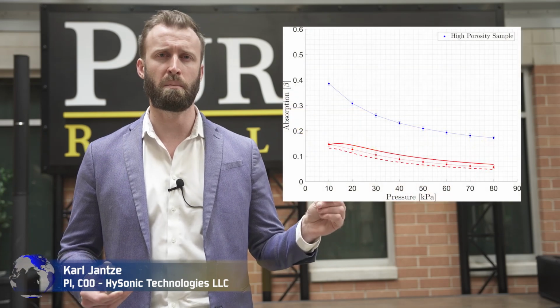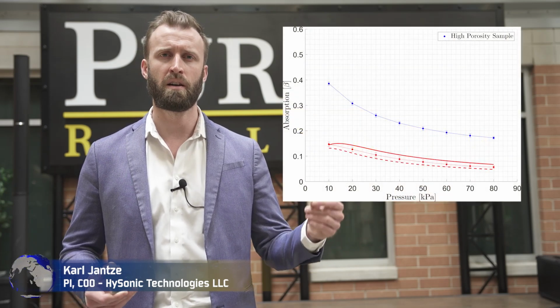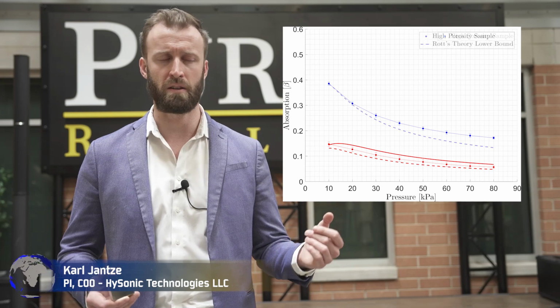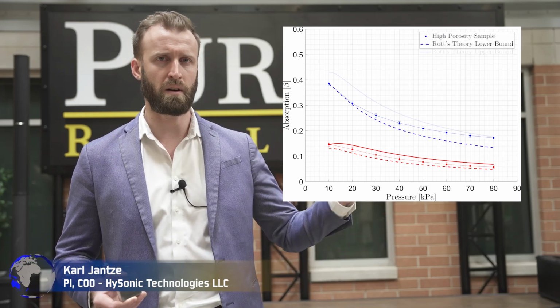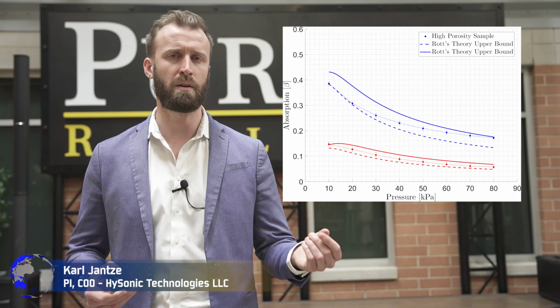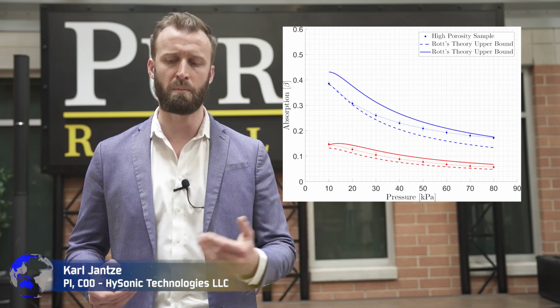In my hand here we have the high porosity sample, and similar to the low porosity sample, it contains pores that have a certain diameter and depth. The only difference is that it has more pores, allowing there to be a greater surface porosity. Very similarly, if we take a look, the experimental data is given by a blue dot that has an error bar, also representing the repeatability of these results. The lower curve and the upper curve also represent a certain tolerance above and below the nominal pore depth.